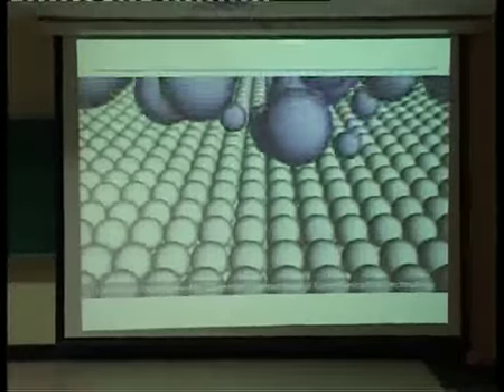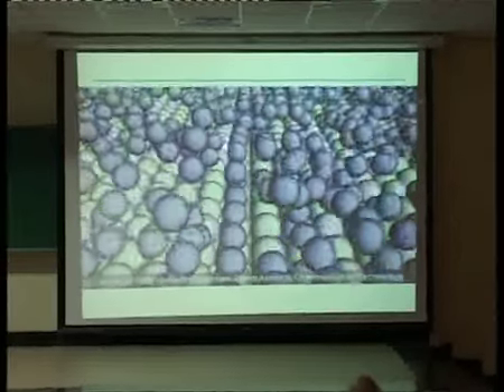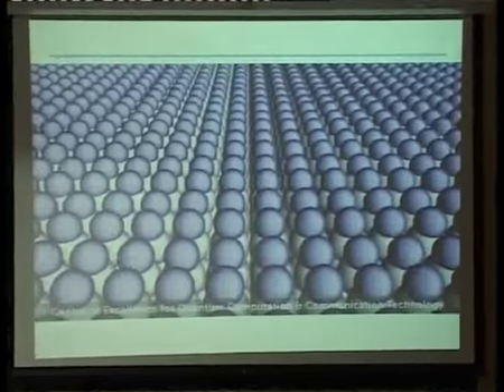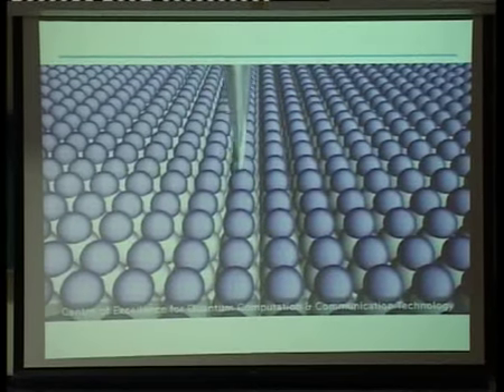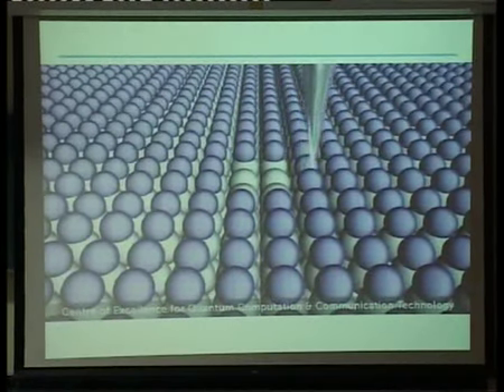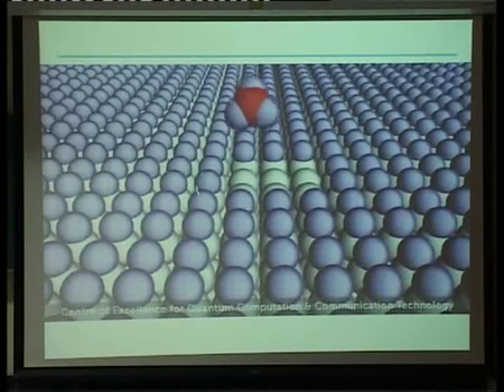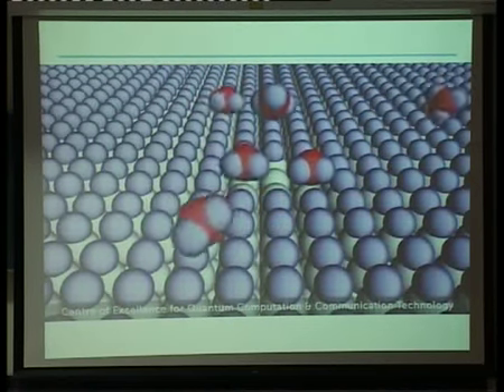And hopefully this movie will go quickly. This is the full fabrication of how we do the single donor. There's our registration markers. We zoom into the atoms on the surface. We hydrogen terminate. We come along with our STM tip and deliberately open up these 6 holes. The thing that we've realized now is that we have to saturation dose this central region to force 3 PH2s into that central region.